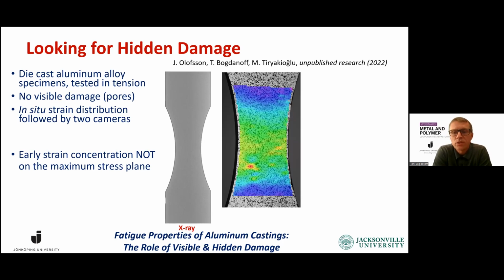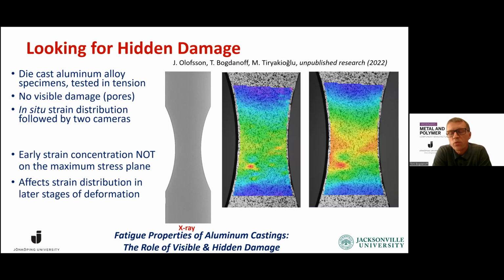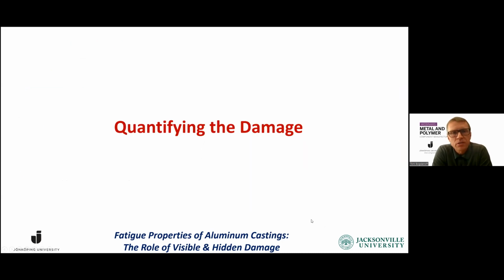So if we continue, we see that the strain concentration moves a little bit and it's a little bit bigger. And this is something that we will continue to investigate, but it's clear that we have something that is not a pore in this case, that makes the damage and makes the fracture in this region of the material. So we have a lot of samples of this, so that will be a future work and something that we will publish in a while.